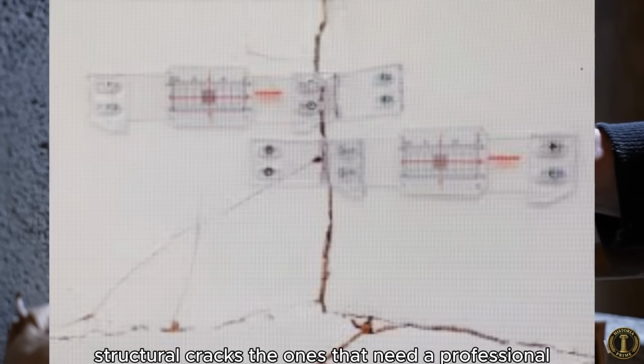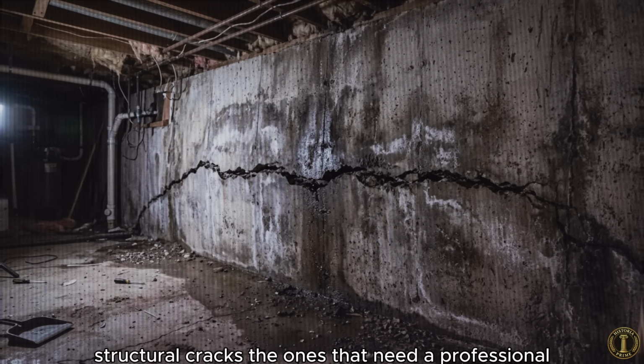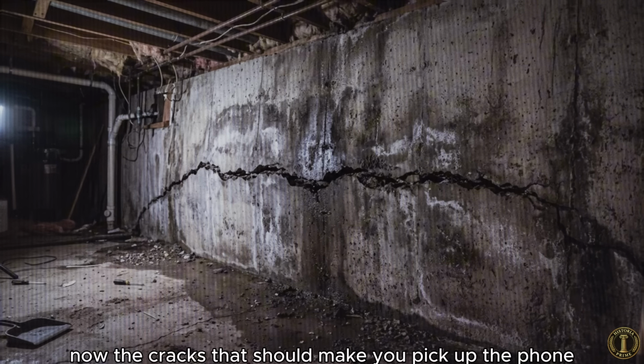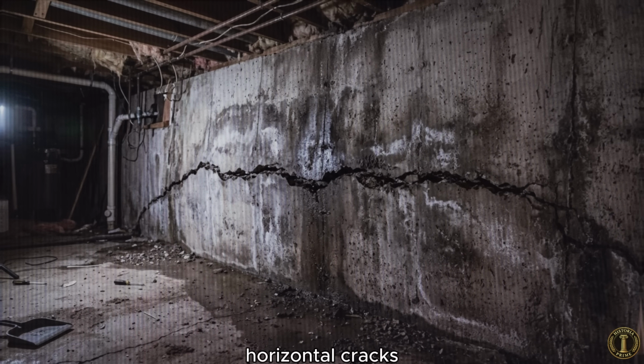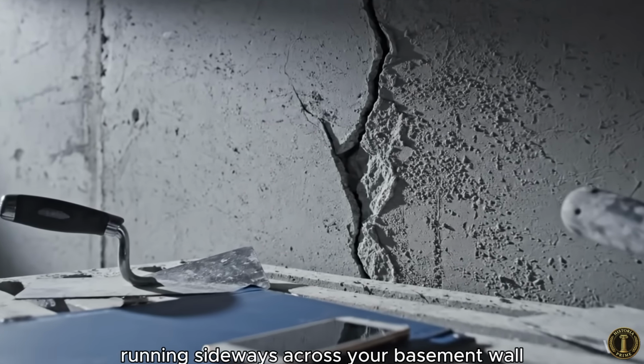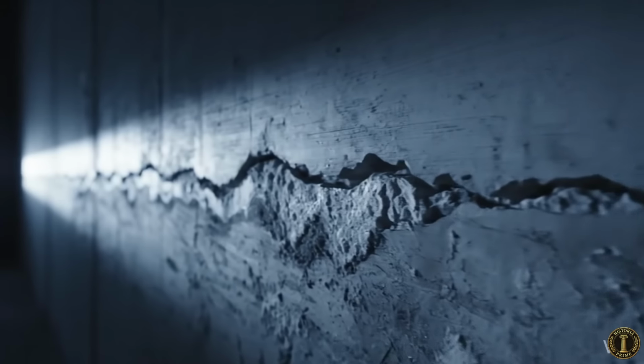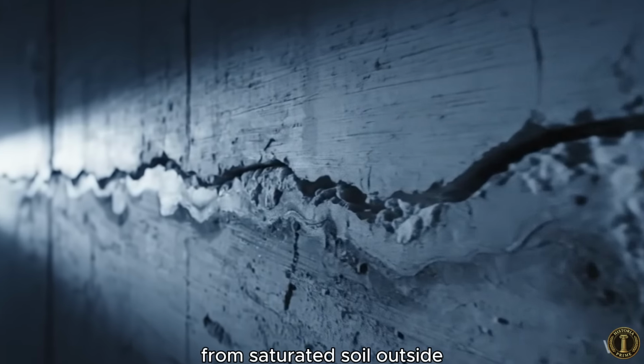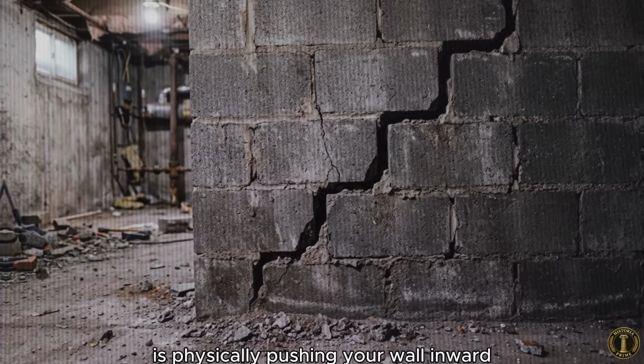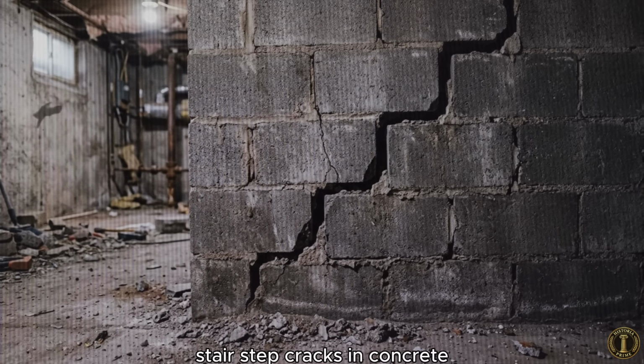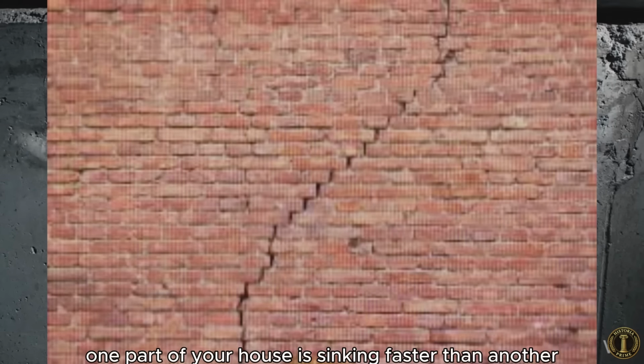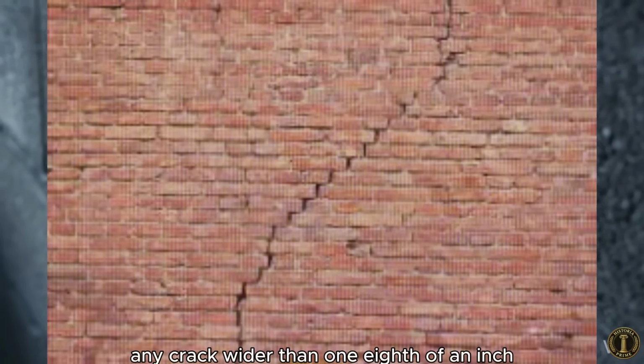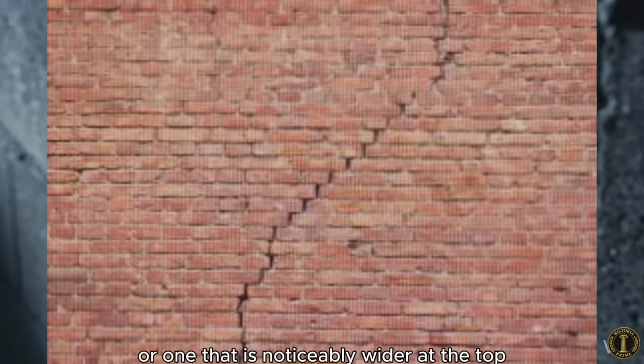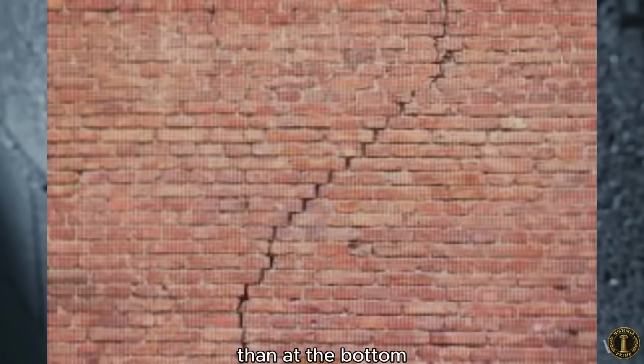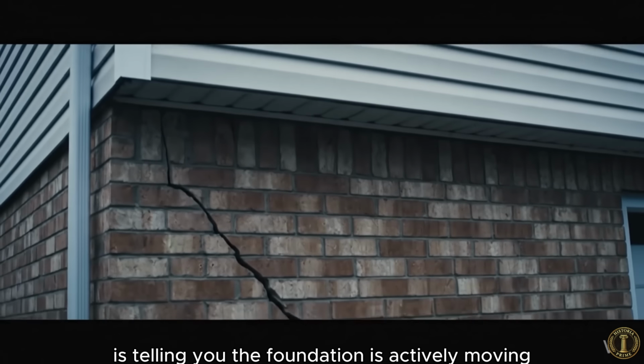Structural cracks, the ones that need a professional. Now the cracks that should make you pick up the phone instead of a trowel. Horizontal cracks running sideways across your basement wall are almost always a serious warning. They indicate that hydrostatic pressure from saturated soil outside is physically pushing your wall inward. Stair-step cracks in concrete block or brick walls signal differential settlement, meaning one part of your house is sinking faster than another. Any crack wider than 1/8 of an inch, or one that is noticeably wider at the top than at the bottom, is telling you the foundation is actively moving.